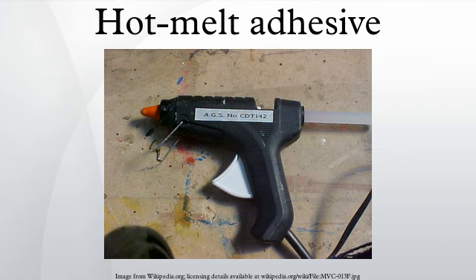Absorption of moisture may lead to foaming during application as water evaporates during melting, leaving voids in the adhesive layer which degrade mechanical strength. Polyamide HMAs are usually composed of a dimer acid with often 2 or more different diamines. The dimer acid usually represents 60 to 80% of the total polyamide mass, and provides amorphous nonpolar character. Linear aliphatic amines such as ethylene diamine and hexamethylene diamine provide hardness and strength. Longer chain amines reduce the amount of hydrogen bonds per volume of material, resulting in lower stiffness. Polyether diamines provide good low-temperature flexibility.